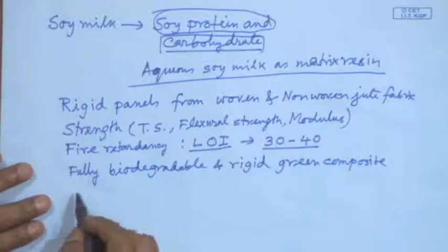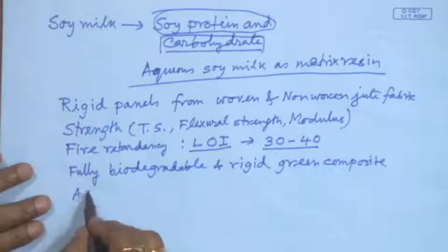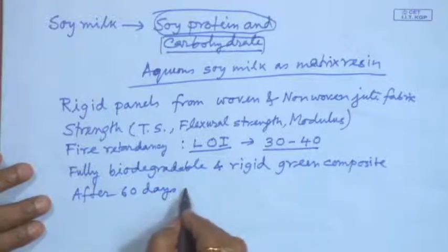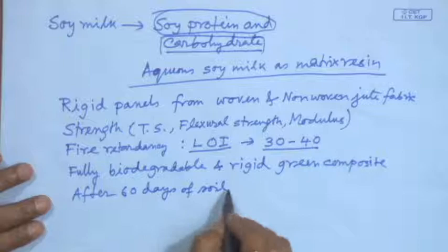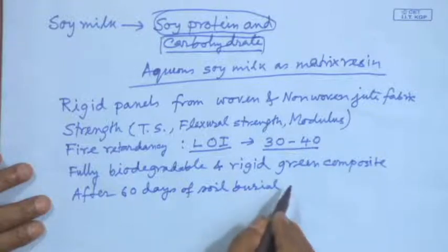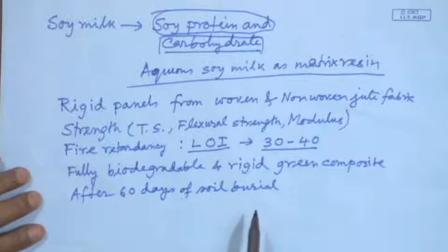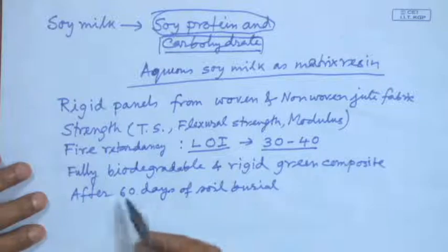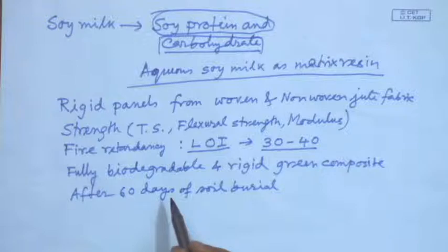We have measured the biodegradation, evaluated the biodegradation characteristics of these composites. We have found that after 60 days of soil burial in compost condition, the composites become brittle and fragmented. So, it shows very good degradation properties during 60 days of soil burial in compost condition, in humid condition, in wet condition.